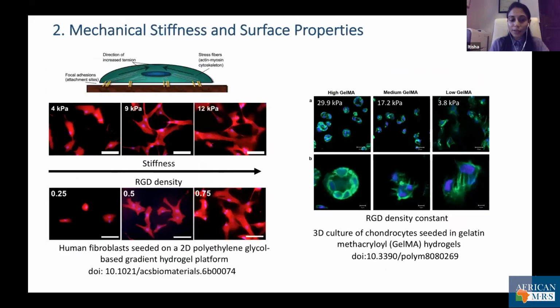Now, other properties of the hydrogels are mechanical stiffness and surface properties. It is known that cells on a matrix attach via integrin-containing focal adhesions linked to their cytoskeleton. So it pulls on the matrix and senses the resistance, and this increases the tension in its structure. So it tends to spread out on the surface. So this is an example of a human fibroblast seeded on a 2D structure, a hydrogel scaffold. So obviously you can see that while increasing the compressive modulus, the spreading increases and also the proliferation increases.